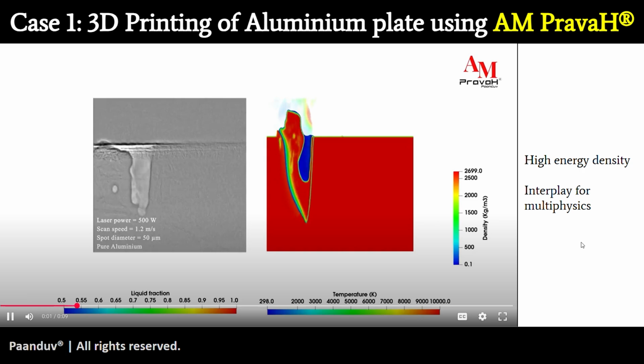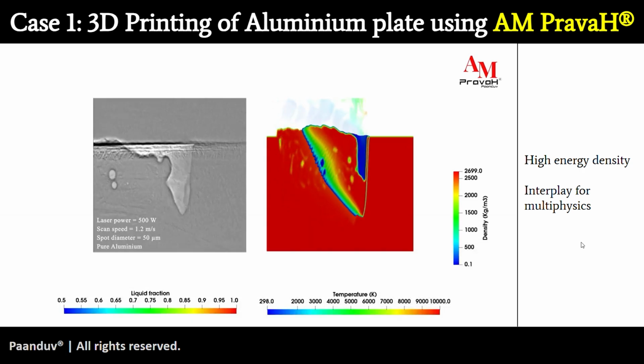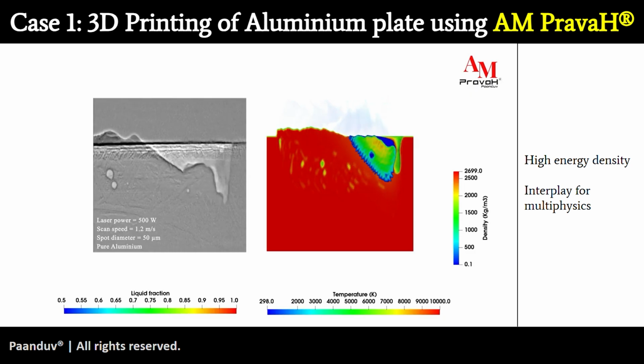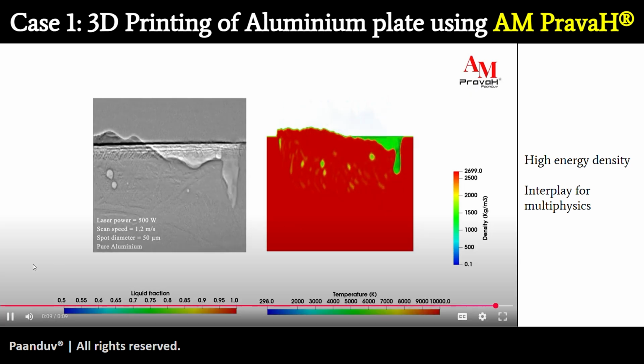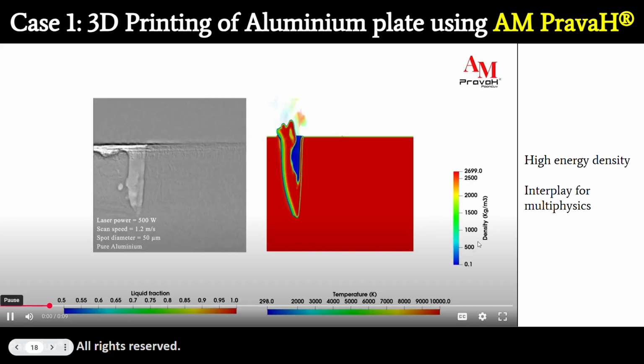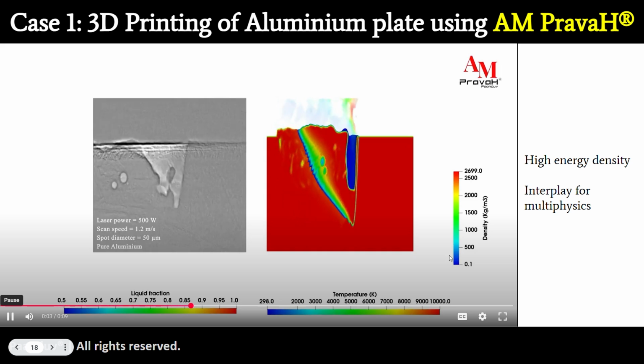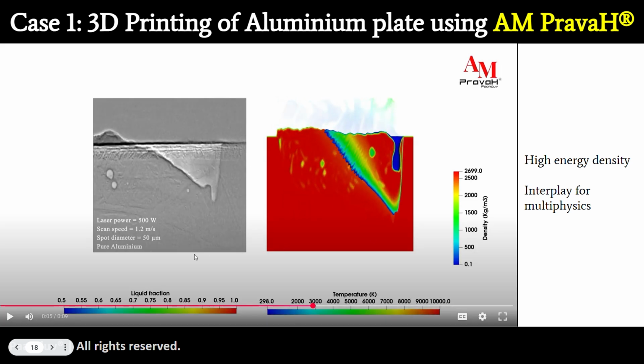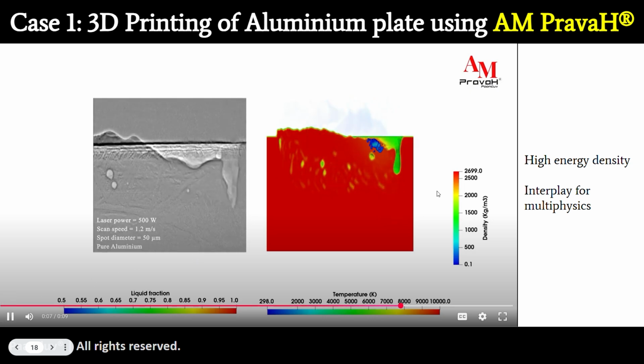Case 1 is the 3D printing of aluminium plate using AM PravaH, high energy density, and there's a huge interplay of multi-physics. I would like to bring your focus to the genuine high fidelity nature of these simulations. Just look at the image on the left hand side, which is coming from the experiments, and the image on the right hand side, which is coming from AM PravaH. Notice the defect formation, the pore formation, the hump formation, and you name it. While this simulation may look quite straightforward, the amount of physics equations that are solved in order to capture